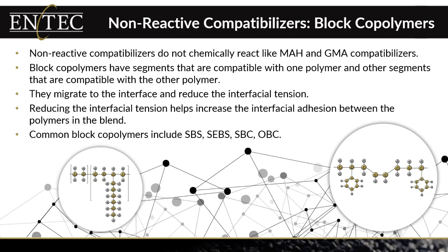And so the very common block copolymers again include things like SBS, SEBS, other styrenic block copolymers, as well as olefinic block copolymers. And typically of the non-reactive compatibilizers, these block copolymers perform very, very well because once again, we have one segment that attaches to one polymer and another segment that attaches to the other polymer, and they bridge across that interface.